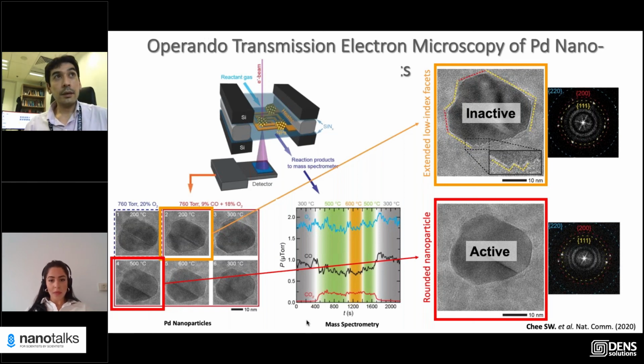Actually, with these climate chips, the drift is not so bad. It's a very gradual drift, so you can compensate for it. But we also use a high speed camera, so we can record the images at a few hundred frames per second, so we can always drift correct. So it's not an issue for us, because you can drift correct and then average, and then you get very crystal clear images. I hope that answers your question.